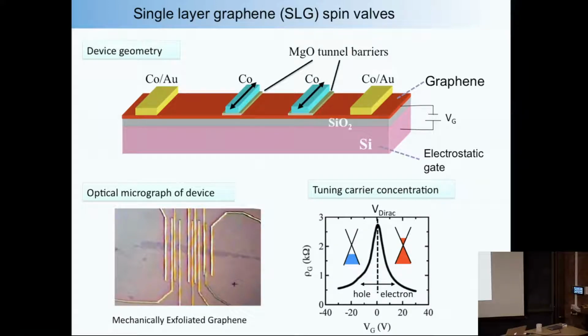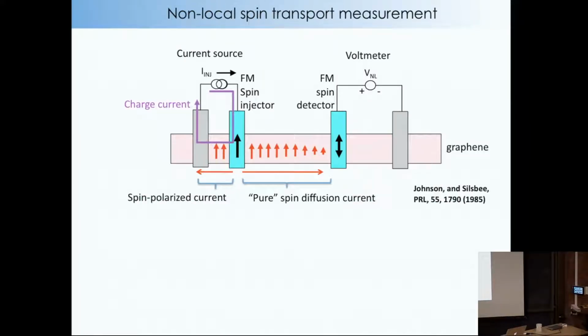If you put a negative charge, it'll attract holes. So you can control the carrier density just by applying this backgate voltage. So you're able to tune this material. You can do this with semiconductors, but say in metals, you couldn't do this type of tuning so easily. Okay. Now in the field, this is called the non-local spin transport measurement.